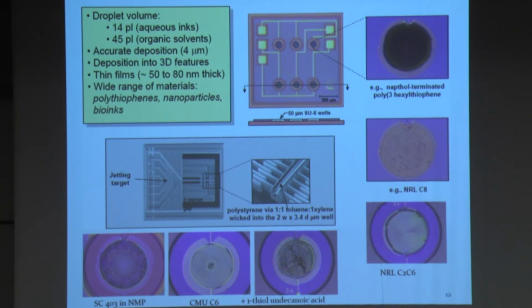So you can make arrays of sensors not only by jetting the materials themselves, but also by jetting reagents to change them. And in the middle, we see another use of our inkjet. When we jet a drop of regular polymer in here, the polymer gets sucked up into the narrow channel, which is about 1 to 2 microns wide, and there's no other way to coat these narrow troughs except for this method. Okay.